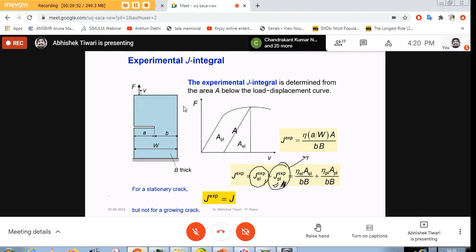So it is not defining the crack driving force, but it is defining the material's resistance. Plastic energy is the form by which the material is responding. It is fighting back against the forces which are trying to break the material. In a nutshell, this J integral will not define the true crack driving force as long as the crack grows. For a stationary crack, we are still loading it and there is no unloading happening. In some cases there will be unloading, but let us assume that for a small amount of deformation, as long as we are just pulling the system and the crack does not grow, we are not unloading it.